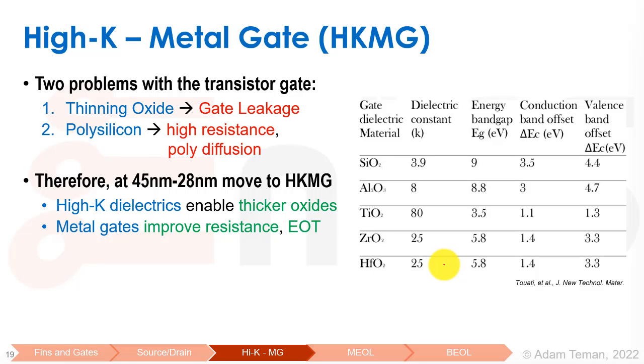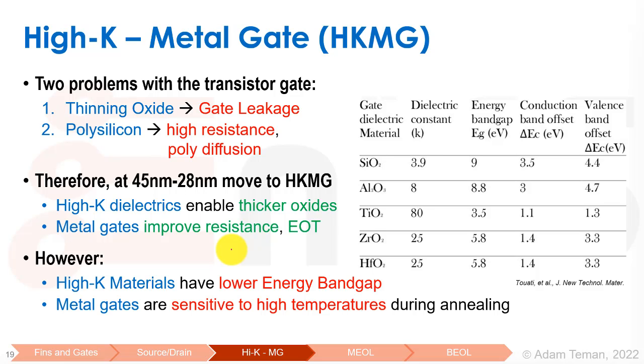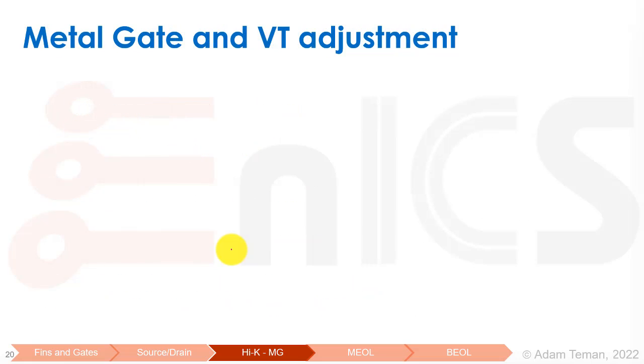The other thing is that metal gates improve resistance. So we can replace our polysilicon with a metal gate. We don't have the resistance of the polysilicon. We have better resistance, with some sort of copper or something like that. And we also don't have this problem with poly depletion that, again, hurts our effective oxide thickness. Okay, so that's why we moved to high K metal gate once we were able to integrate these high K materials into the process. However, the high K materials have a lower energy band gap, and metal gates are sensitive to high temperatures during annealing, so we have to do all kinds of tricks.